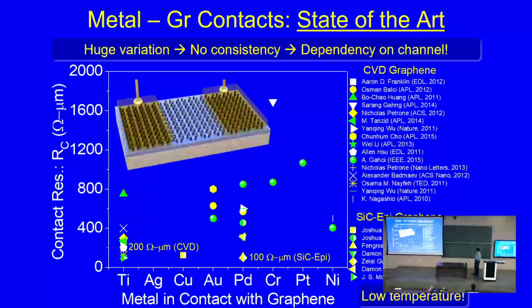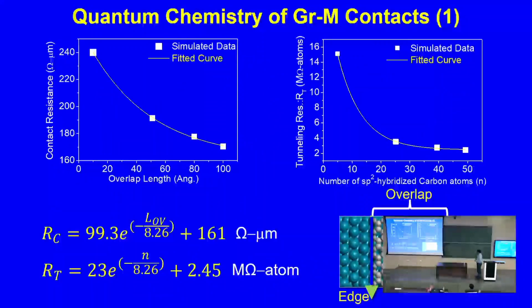In case of graphene, the best numbers reported were, for silicon carbide, which is the best quality graphene, as expensive as diamond, 100 ohm micrometer, and for CVD 200 ohm micrometer, but measured at 4 Kelvin, not room temperature, right? Room temperature was somewhere here, the best numbers. So we started digging into the quantum chemistry, right? Out of many experiments, what you see is what has worked. I'm not talking about what did not work.